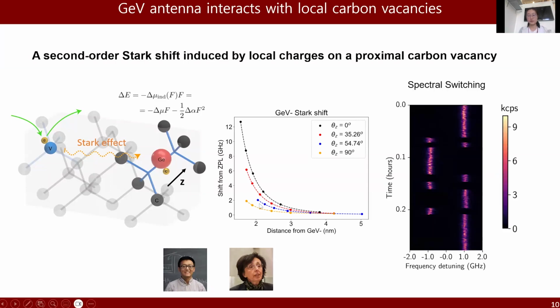In most cases, when we took the PLE spectrum, we observe that the GeV has a single narrow peak. But in some cases, we observe some GeVs that exhibit a ZPL splitting magnitude of hundreds of megahertz to a few gigahertz, and spectral hopping between these two distinct energies. This means that the GeV has a local carbon vacancy in the proximity.